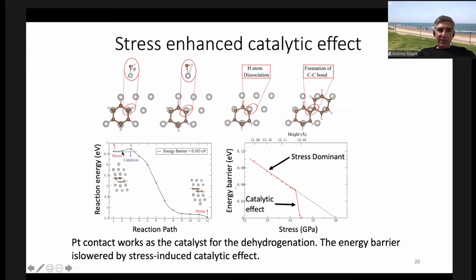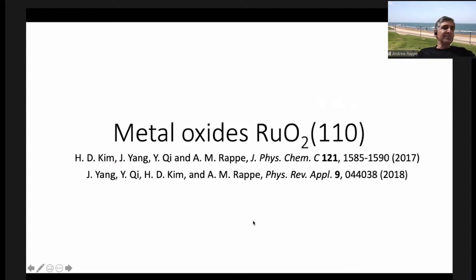So initially you have your benzenes, there's a reaction barrier, and they would actually like to bond. That's the lower energy state. But if you start to apply stress, you see a linear dependence in the barrier. It starts with a high barrier, which gets lower and lower and lower. And when you get near the point where you think the stress would reduce the barrier to zero, it actually falls off to zero faster. And we ascribe that to a catalytic effect. So most of the behavior is stress favoring the reaction. And then a little bit, the catalysis of the platinum is helping also. So that's how this reaction happens.